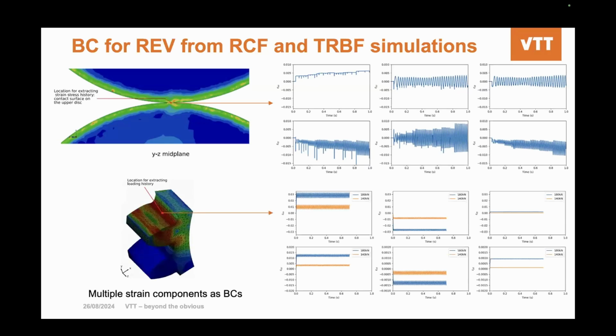This picture shows the 6 strain components we extracted from the rolling contact case. We can see the actual strain in the x-axis direction, towards you, gradually increases due to the gear rolling. We have plasticity in the model, so we have a flattened behavior, and we also noticed significant shear components. And for the gear root bending test, we have simulated 180 kilonewton and 140 kilonewton pulsating force. Apparently, the higher pulsating force gives higher tension strain in the X direction.